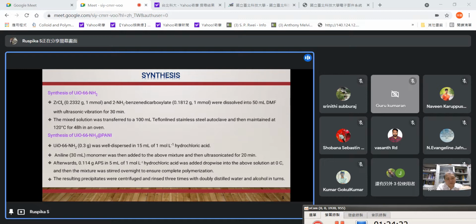For the synthesis of UiO-66-NH2 at polyaniline, it was dispersed in hydrochloric acid, and aniline was added to the mixture and sonicated for 20 minutes. Then the APS solution in hydrochloric acid was added dropwise, and the mixture was stirred overnight to get complete polymerization. The resultant precipitate was centrifuged and rinsed 3 times, and washed with double distilled water and alcohol.